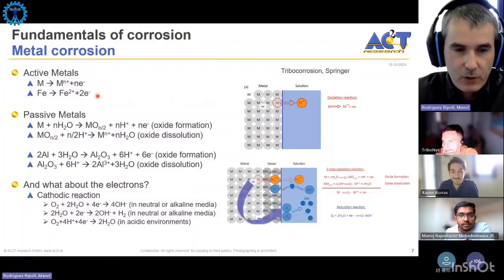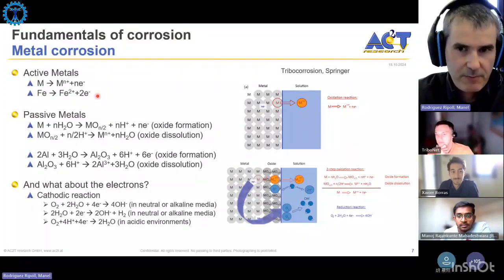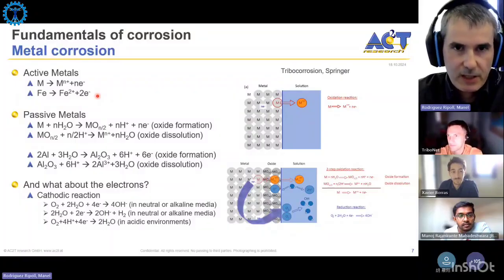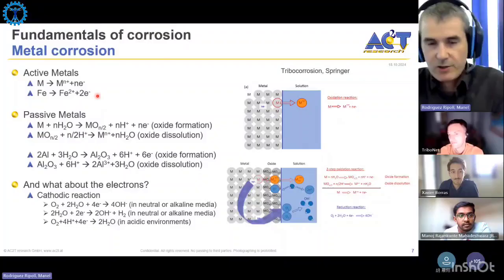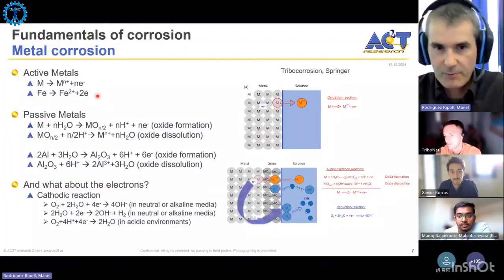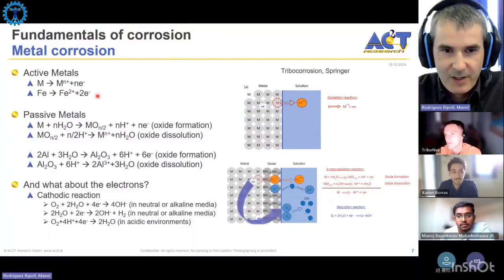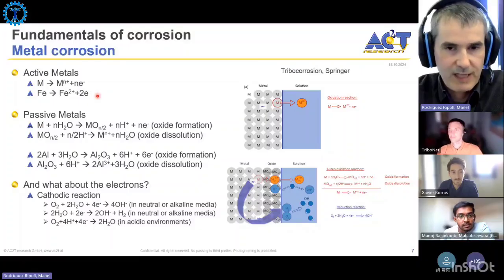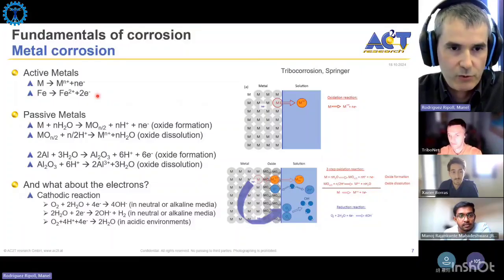Well, the corrosion potential can take quite a long time to stabilize. Typically in tribocorrosion experiments, the typical time that I use for stabilizing the OCP is 30 to 60 minutes. But what is important here is the rate of variation, because you have a trend, a tendency to reach equilibrium, but you would need infinite time to reach it. When the OCP is changing less than, let's say, 1 millivolt per minute, you can then stop and consider the OCP to be stable. But typically 30 to 60 minutes could be sufficient.